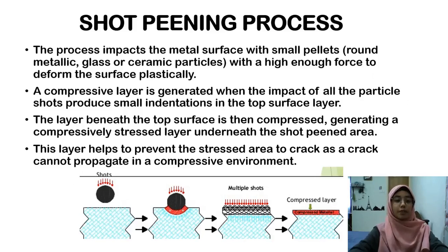For the shot peening process, firstly the process impacts the metal surface with small pellets, round metallic, glass or ceramic particles with a high enough force to deform the surface plastically. A compressive layer is generated when the impact of all the particle shots produce small indentations in the top surface layer. Next, the layer beneath the top surface is then compressed, generating a compressive stress layer underneath the shot peened area. This layer helps to prevent the stressed area from cracking, as a crack cannot propagate in a compressive environment.